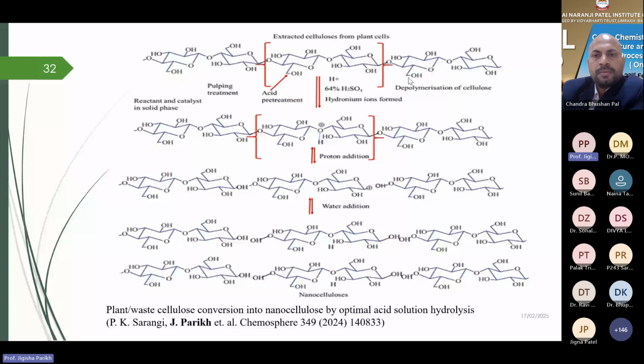So we first require a pre-treatment process to loosen the material, because after that we require the depolymerization of the cellulose to provide us with the nanocellulose. So we have to loosen the structure. For that we need some water addition and hydrolysis, and then acid pre-treatment is also helpful for that kind of structure. To break these bonds, acid pre-treatment is required, and then hydronium ions are required for the protonation reaction. Otherwise this branched structure will not break, and we have to break it through these ethers. Okay, so the amorphous and crystalline regions of cellulose microfibers are distributed randomly along their path.